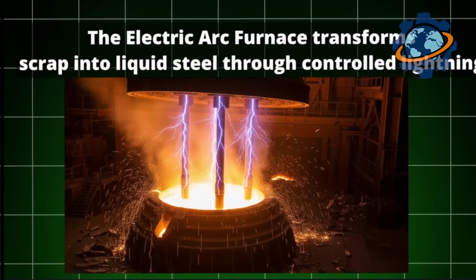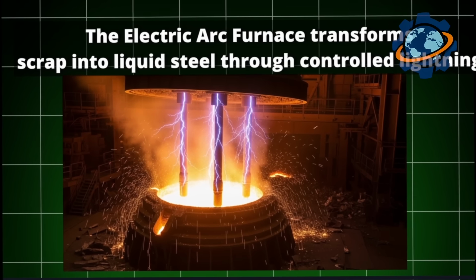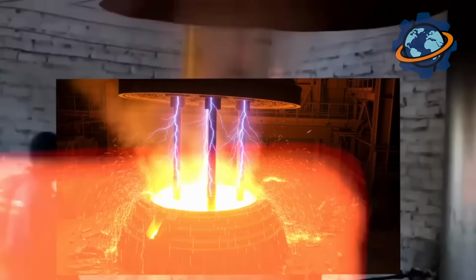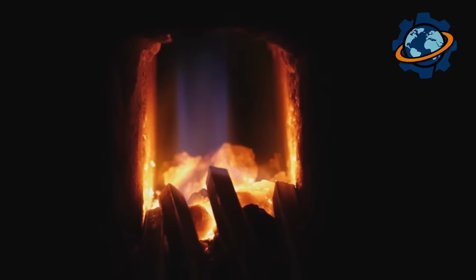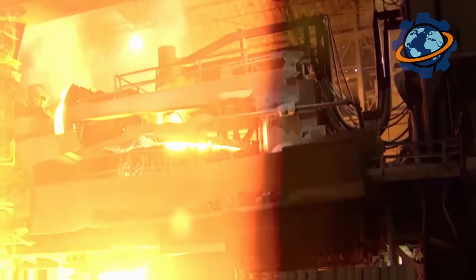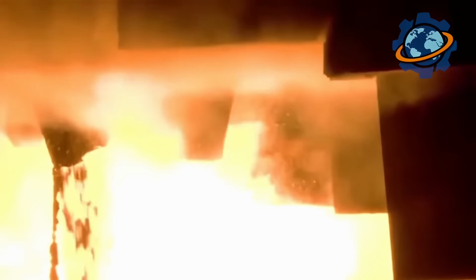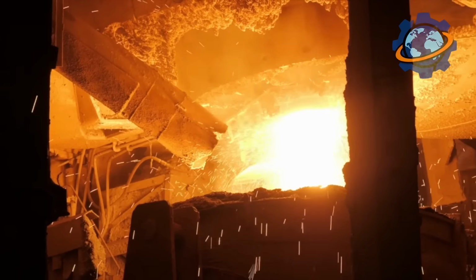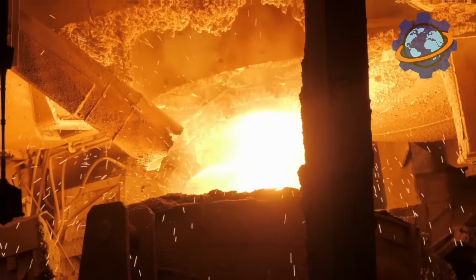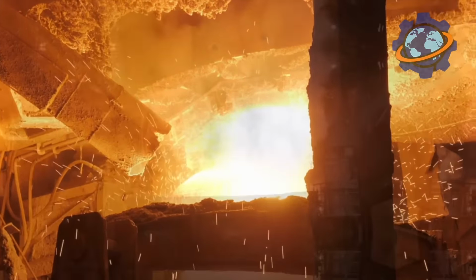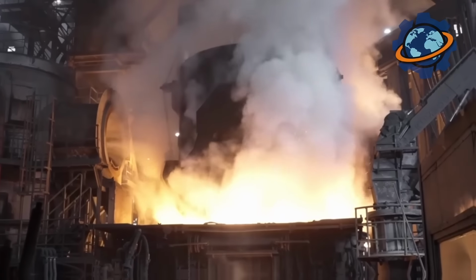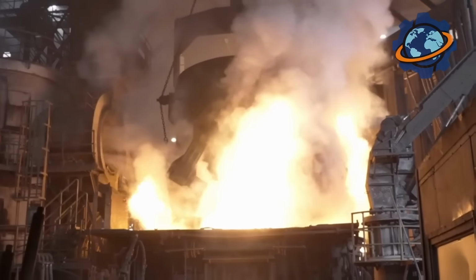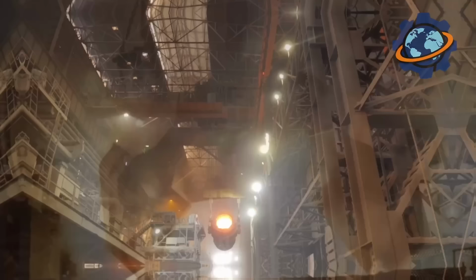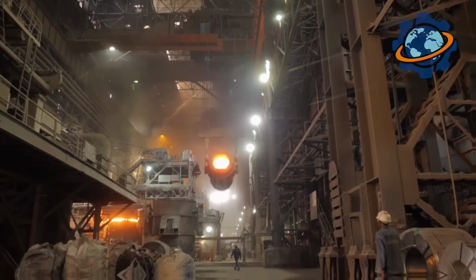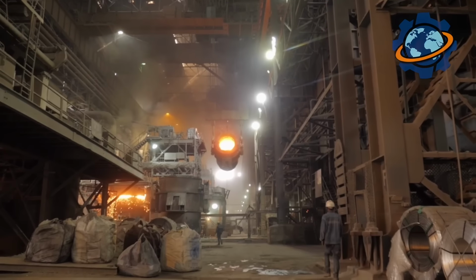The electric arc furnace transforms scrap into liquid steel through controlled lightning. This vessel, 40 feet diameter and 30 feet deep, contains 3 graphite electrodes 2 feet thick descending from roof. When 90 megawatts flow, power for 70,000 homes, arcs jump between electrodes and scrap, generating 5,800 degrees. The scrap melts in minutes. Watch through protective glass as metal liquefies, glowing white hot then orange as temperature stabilizes.